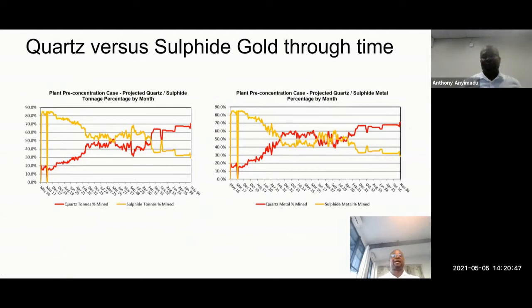Okay, so what is the economic opportunity here? In this case, the two things you are seeing are tons of material that is quartz-linked versus sulfide-linked, and then, on the other hand, the actual gold content. So you're talking about the same thing, but in a slightly different way. Currently, which is around 2021, sulfide gold is still around 50 to 60%, and the quartz gold is making up the rest, about 40%.